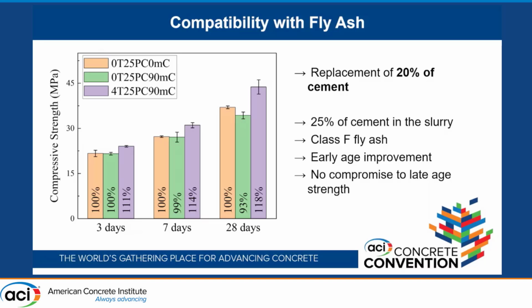So first, we're going to look into the compatibility with the fly ash. All three samples have 20% of fly ash, and in this case, it's class F fly ash. And we have 25% of the cement in that slurry, so a little bit higher concentration, and we're going up to 90 minutes of carbonation. For reference, we have the 20% of cement, no carbonation and no tannic acid. And then in green, we have the carbonation without the molecule, and you can see that it actually hurts the strength,